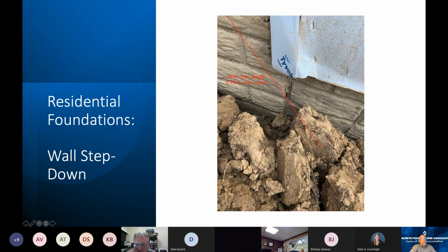And so what they ended up getting in this particular case was, because it's a downward pressure on this step down condition, instead of the diagonal crack, they ended up getting it to go down a vertical plane. You can kind of see it on the right-hand side, just as the frame condition meets a vertical form seam, and there's a vertical form seam right here underneath the Tyvek, and so it was cracking right there.